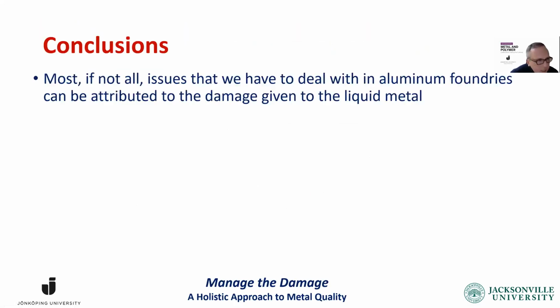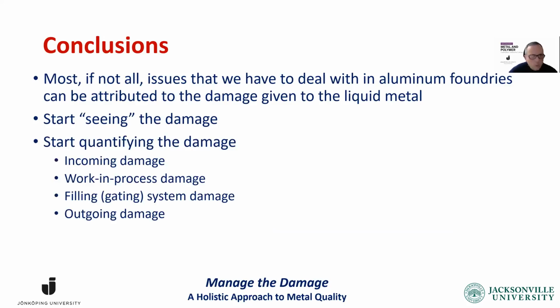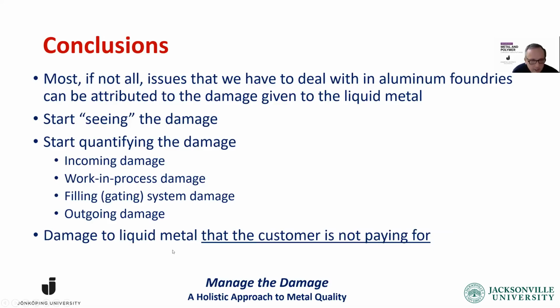So in conclusion, most, if not all, of the issues that we deal with can be attributed to the damage given to the liquid metal just because we treat it like water. We have to start seeing the damage, where it comes from, and when you start seeing it, you cannot unsee it. Then you cringe when you see it. Then we can start quantifying the damage: incoming, work in process, filling system, outgoing damage, the damage given to the liquid metal that the customer is not paying for. The customer wants good product from us, but maybe they don't.